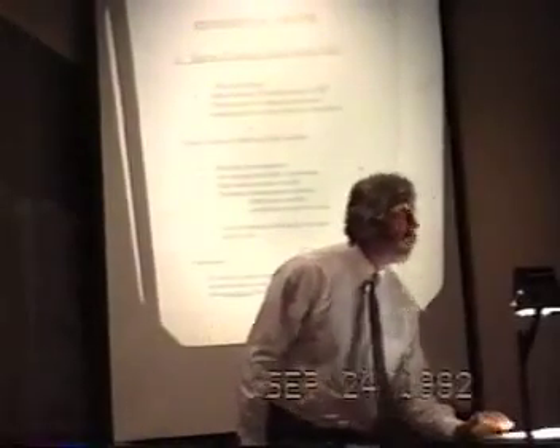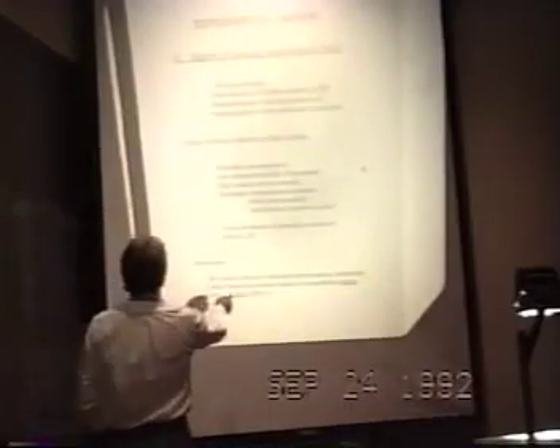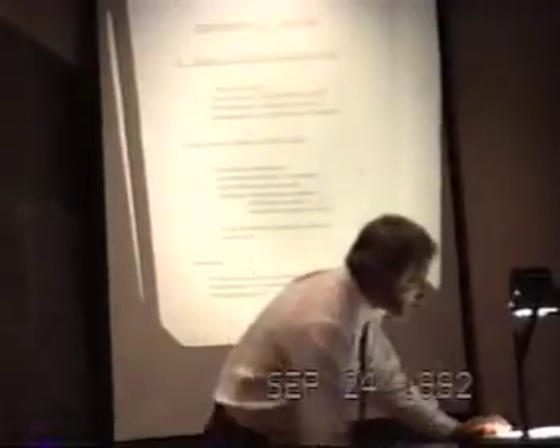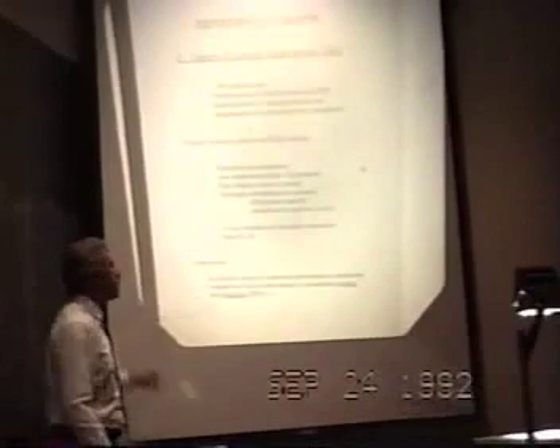I have on this slide the experimental parameters of this set, and I'm going to describe them no further than to say that in order for us to obtain and maintain high loadings, we must form in situ on the surface of the palladium cathode in its alkaline electrolyte a film where the constituent parts of this film contain the elements either silicon or aluminium, and others may be possible. Our conclusions are somewhat at odds with some electrochemical conjectures in the last few years, but by no means at odds with the known electrochemistry of the hydrogen-palladium system in the 20s, 30s, 40s.